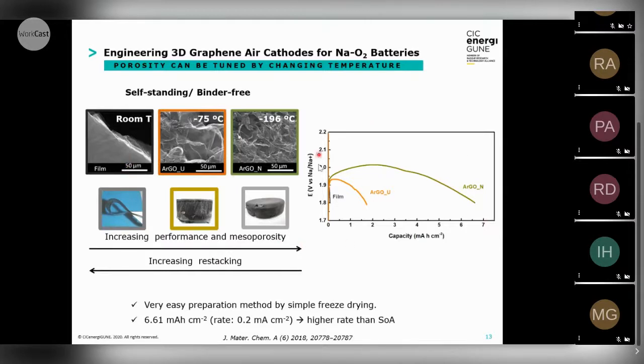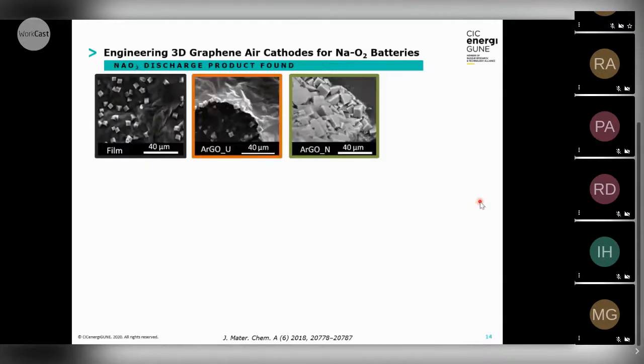And this we correlate with the electrochemical performance in a battery where we use sodium metal, an organic electrolyte, and this freestanding cathode. We can see that with the film we cannot even get any capacity, but then with the sample which presents larger mesoporosity, we can get nearly 7 milliamp hours per square centimeter at quite high rate, if we compare with the state of the art.